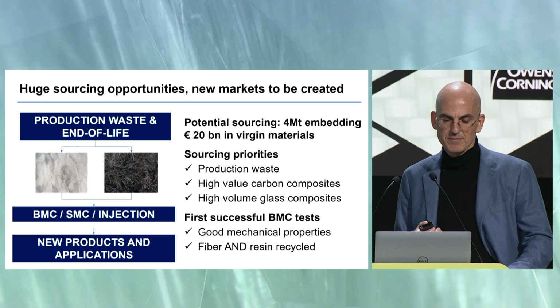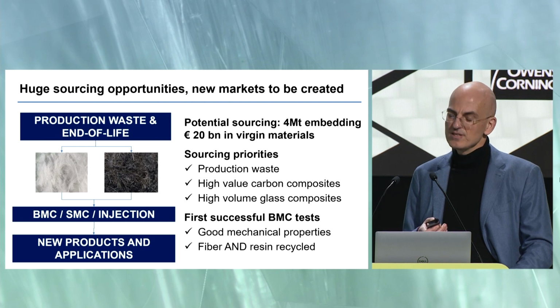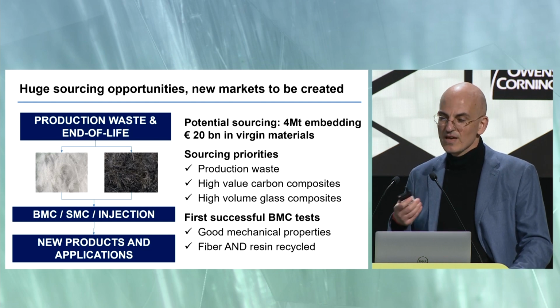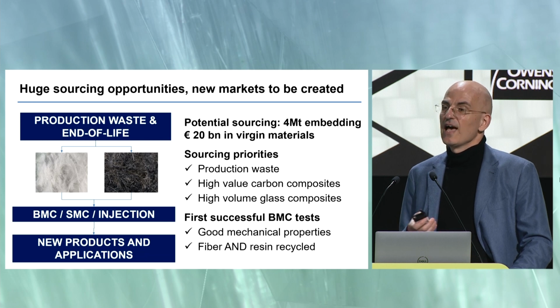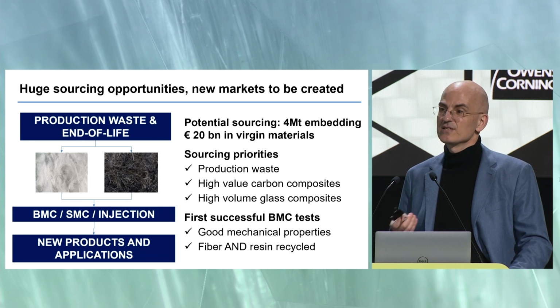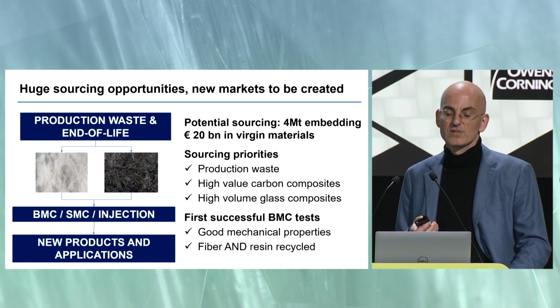So the idea, you see pictures of the fibers or the fiber bundles, if you prefer, that we can obtain with our process. We can then reintegrate them in composite through various technologies, BMC, SMC, or injection. And we have started to do this. And with BMC, we have produced some parts, and the mechanical properties of these parts were very good. And actually, it's a way not only of recycling the fibers, but also the resin, which remains in these fiber bundles. So we need less resin to produce new composites.